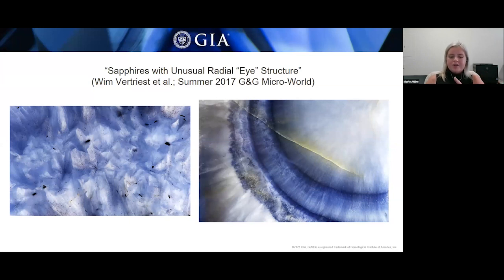And this is evidenced in the photomicrograph on your right, that epigenetic yellow goethite that you can see in that fracture. If that stone was heated, even at relatively low temperatures, that goethite would actually alter to a rust-colored hematite.